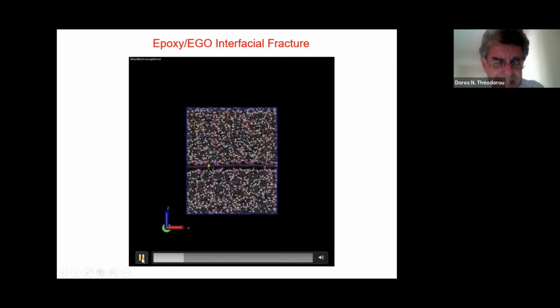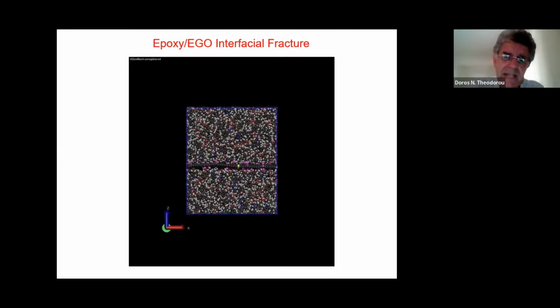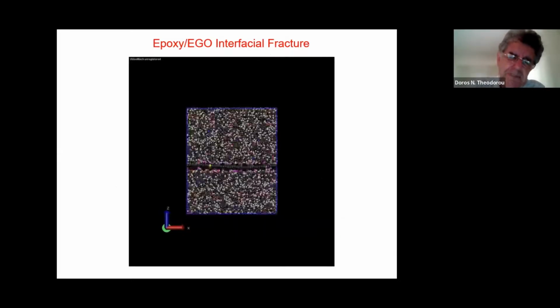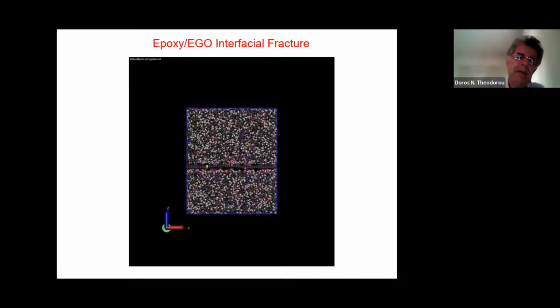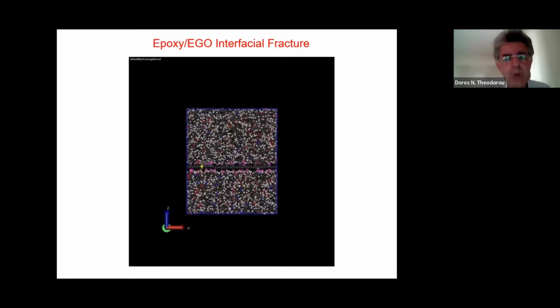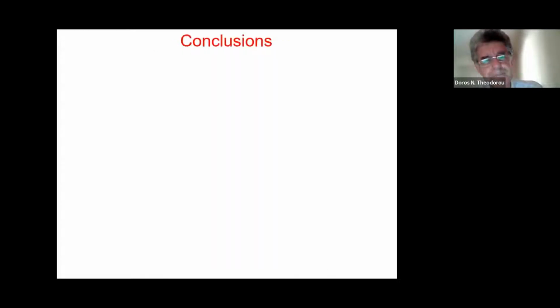So when you impose the stress, initially nothing happens, but then the system fails, and stick-slip behavior ensues, where you see that the graphene slips with respect to the polymer, and the velocity of the stick-slip behavior one can actually estimate quite well from the failure times and the surface unit cell of the graphene.